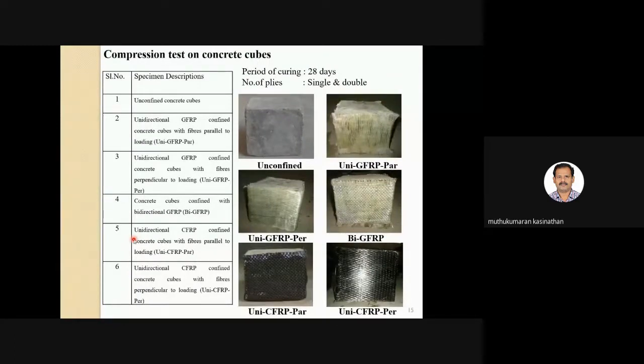So the process has been started like this. Basically, as I mentioned, our intention is to get the enhanced lateral capacity of the pile. As we know, when you use the fiber filament perpendicular to the loading direction, normally the enhanced capacity is much higher than the parallel orientation. We just want to see that. Carbon fiber is unidirectional, but the glass fiber is both unidirectional and bidirectional. So we want to see the complete mechanical characteristics of this material when the fiber orientation is changed. So we have selected both parallel arrangement as well as perpendicular arrangement with respect to the compression test. This exercise will give a clear idea about the load transfer mechanism in the real field analysis.